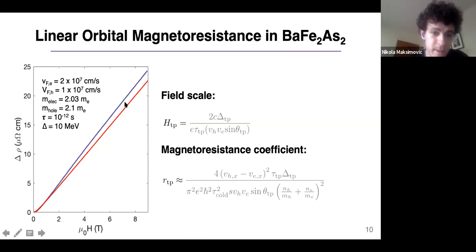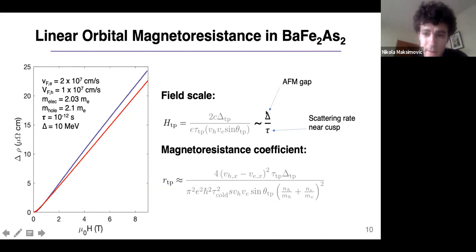So blue is the experimental data, and red is the calculation using these parameters. There's a lot of uncertainty in these parameters, so this should not be taken as quantitative proof that the model is correct, but more of just a sanity check of the model. Something interesting to note is that these magnetoresistance parameters depend on the antiferromagnetic gap. That determines how cuspy the Fermi surface will be. And because that strong turning point region primarily dominates the magnetoresistance, the relevant scattering rate is the scattering rate near that cuspy region, as opposed to the average scattering rate on the Fermi surface.